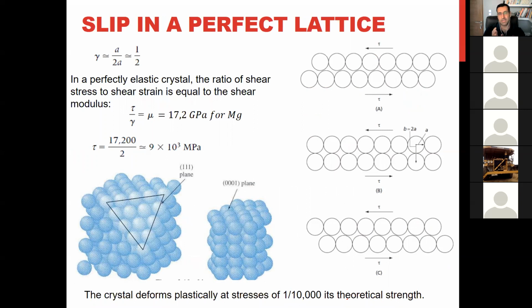So we can calculate theoretically how much shear stress is needed to move two planes over each other. And as we were talking about magnesium, this slide is calculated for magnesium. So if you want to move one plane to this plane, and the distance between these planes is 2a, the movement will be a, so the shear strain that happens by this movement will be half, like this, okay? And we know the shear modulus of magnesium, so we can calculate the shear stress needed for movement of these planes in magnesium, which is about 10,000 megapascal.